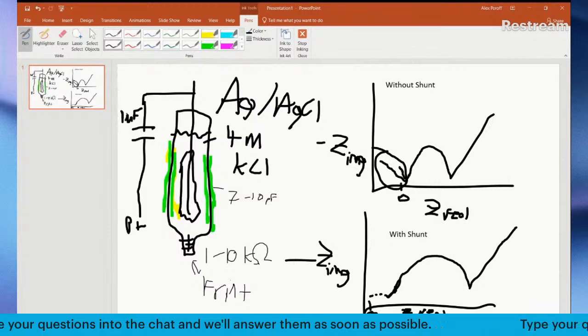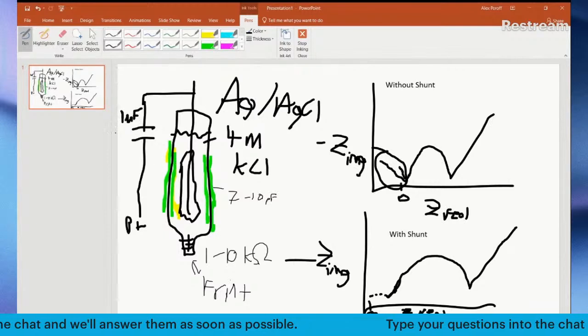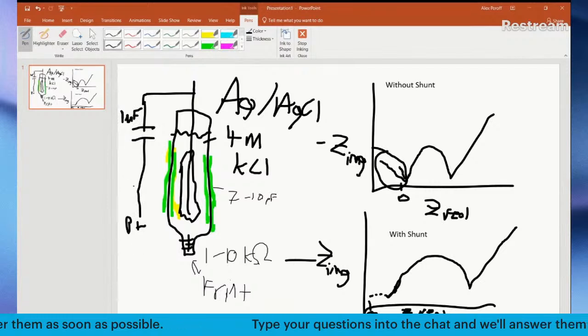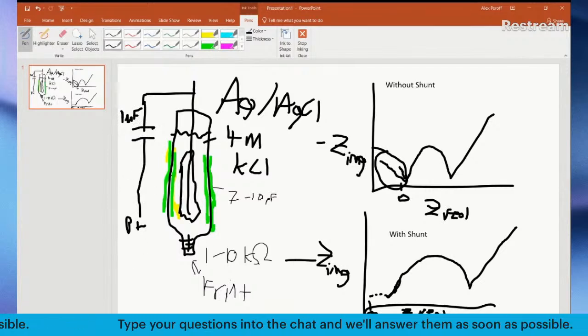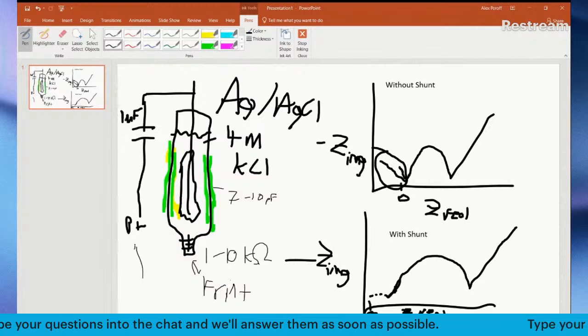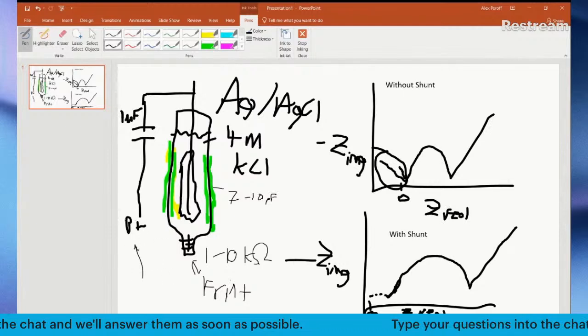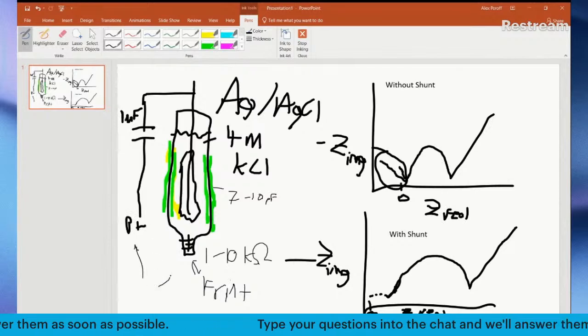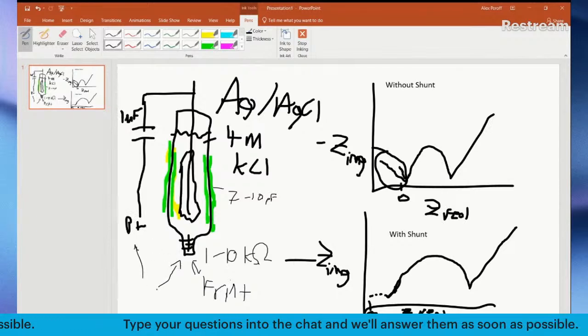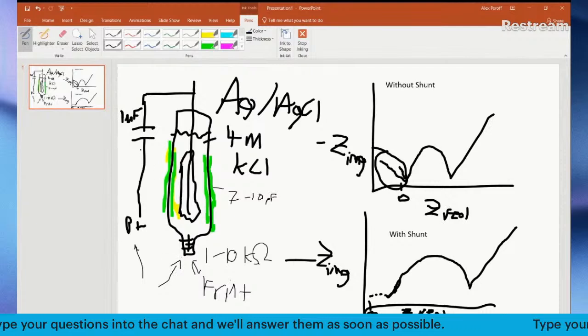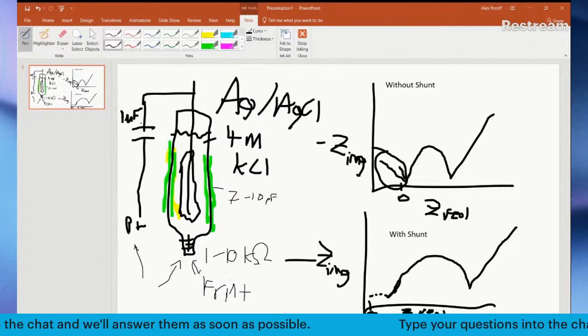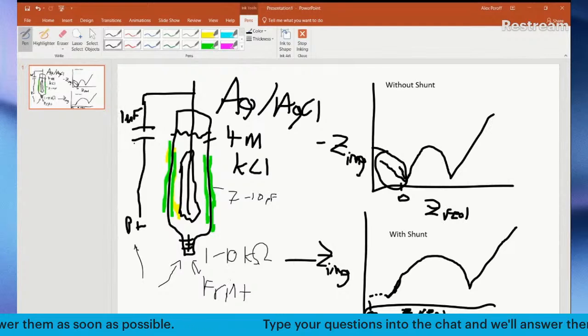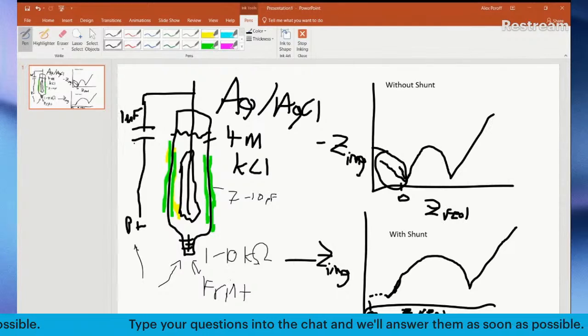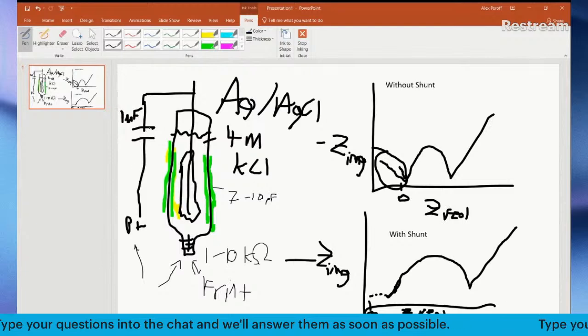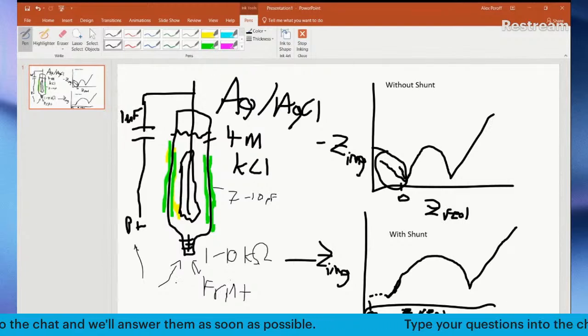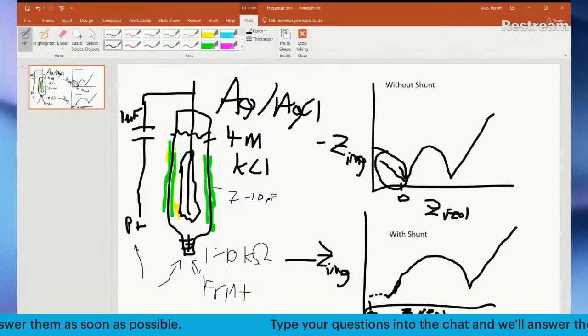And so by virtue of having a 1 microfarad, a larger capacitance, with a very low resistance platinum wire, the current tends to flow here, at least the little bit of current that's used in a measurement, versus current flowing here at high frequencies. This is the path of least resistance, and it dramatically minimizes the phase lag associated with the capacitance in this reference electrode.